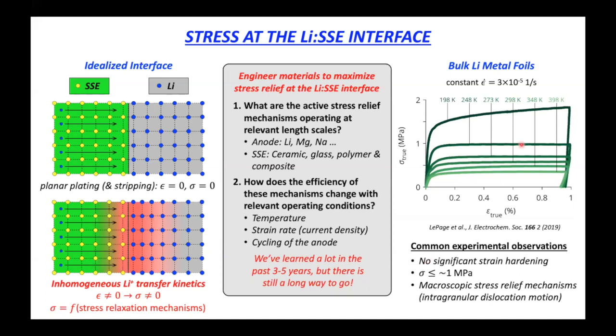And so clearly the mechanical properties of bulk lithium metal are really important to us, right? But the mechanism of action that limits the pressure in this case to 1 megapascal, that mechanism may be completely inoperable at the length scales of these local inhomogeneities, these stress concentrations that are forming at this critical interface. And without those mechanisms, it's not clear what happens, or at least it'll be more clear after this presentation, what happens when that mechanism is not available to keep the pressure at or below this 1 megapascal threshold, right?